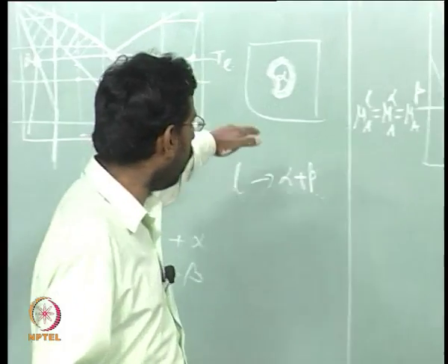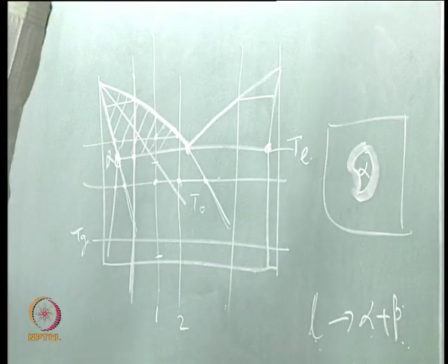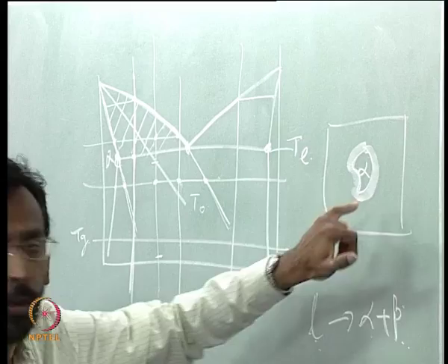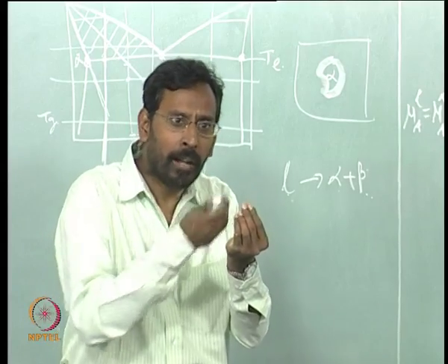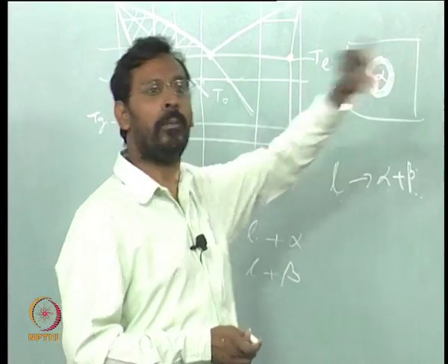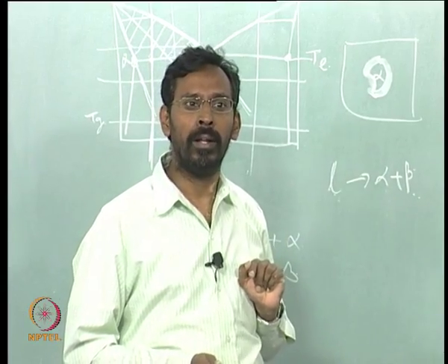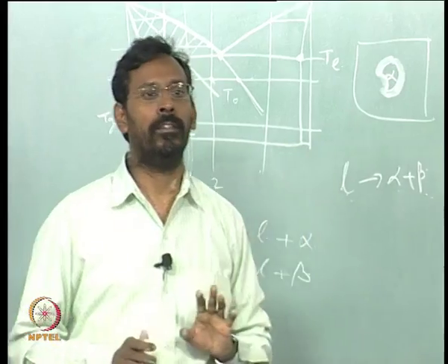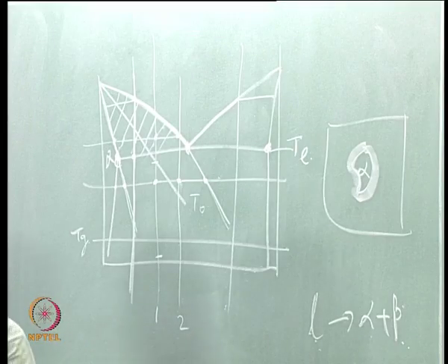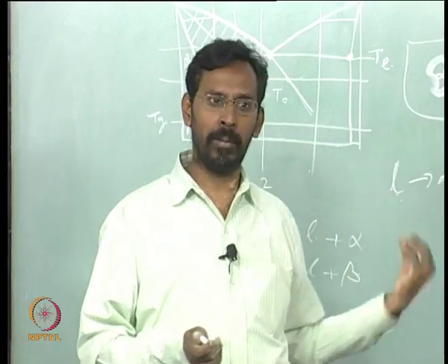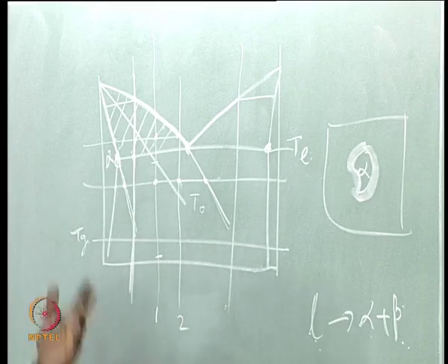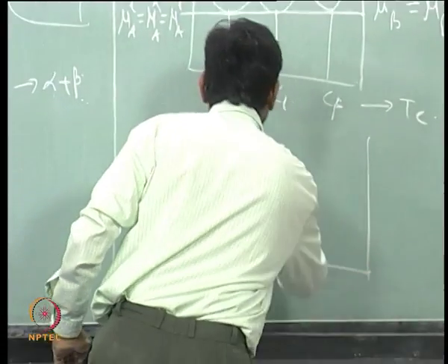where diffusion is easier or not. Similarly, if we are talking about a material which has a sufficiently high melting point, and temperatures close to room temperature, where this also cannot happen, inside the liquid atoms cannot move to come to the composition decided by the local equilibrium, then liquid will not give you that alpha. Even for liquid to give you that alpha, atoms have to come together and form a structure, an FCC or a BCC structure, having this composition. Because now at this temperature, if I simply draw the free energy composition diagram, I have a liquid.